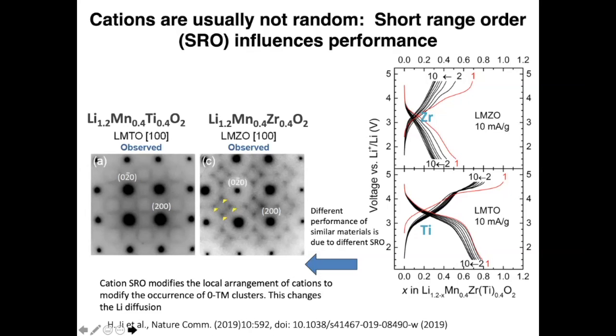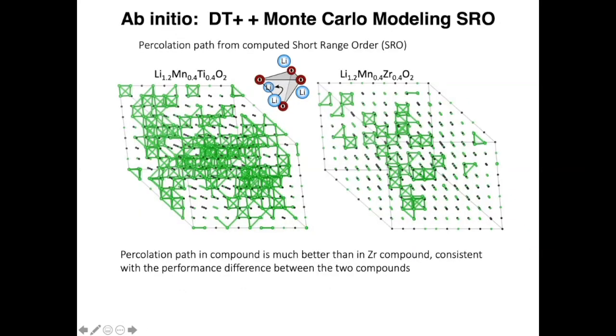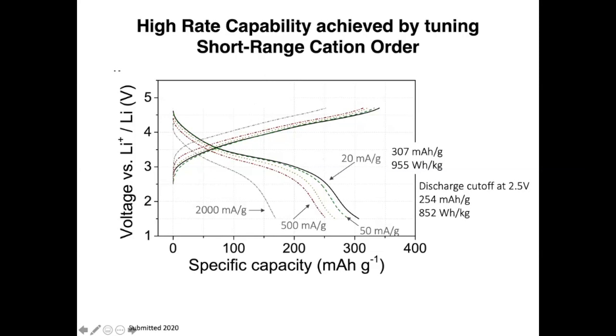If you do a simulation and you plot the zero TM channels, this is the titanate, this is the zirconate, because of the typical near neighbor correlations, the short range order correlations in the ion, the titanate has very good percolation, as is shown here by the green tetrahedra. These are the zero TM channels. As you can see, they connect really well. Whereas in the zirconate, you have exactly the same composition, exactly the same heat treatment, but you actually have very poor percolation. And this is consistent with the observed short-range order and performance.